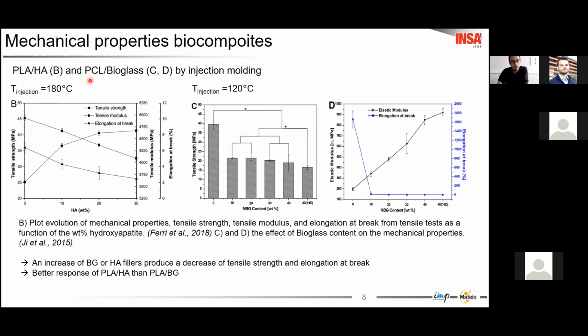We can see that the processing temperature is different for each biocomposite: for PLA hydroxyapatite it was about 180, and for PCL bioglass, 120. We can see that the tensile strength and elongation at break decrease as the content increases, while the modulus increases in both cases as the content increases. In the next part, we will see why the temperature was lower for the PCL bioglass.